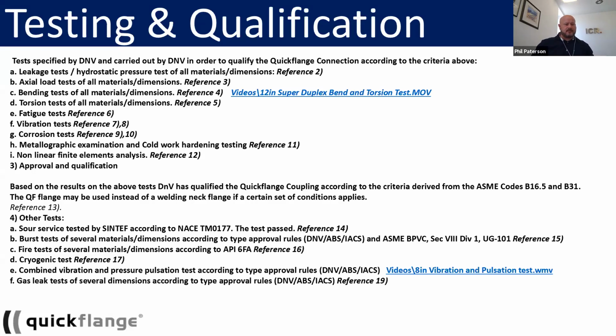So for example, one of the great ones is the fire testing. As we all know, flanges are not fire safe anyway, but the client wanted to use this on a fire header system and wanted to ensure how a Quickflange connector would respond or react under fire state. So we actually carried out an API 6FA valve fire test where we subjected it to 750 degrees Celsius under flame for half an hour with a spool pressurized at 20 bar pressure. We did that both for carbon steel and copper nickel pipe with no failure.